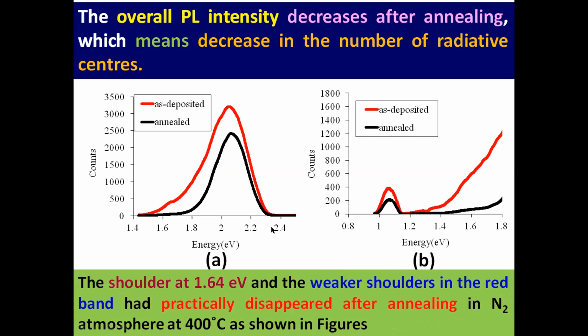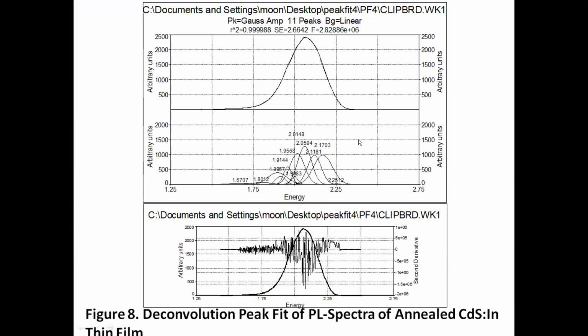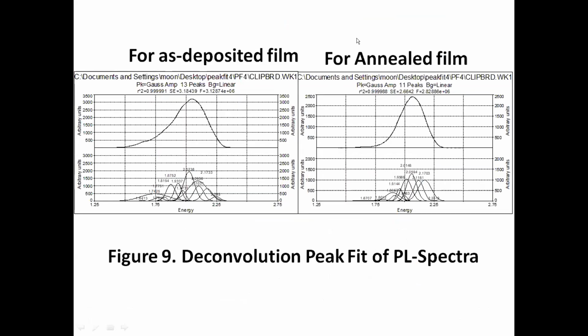Now here is the deconvolution for the PL spectrum obtained after annealing. We got 11 peaks, and also the second derivative was found to confirm the position of the peaks. As you see, the position of the yellow band, now blue shifted, is 2.0594 electron volt. Here is a comparison between as deposited and annealed film. You see the number of peaks is decreased from 13 to 11, and the peaks corresponding to the red shoulder in the red region disappeared.